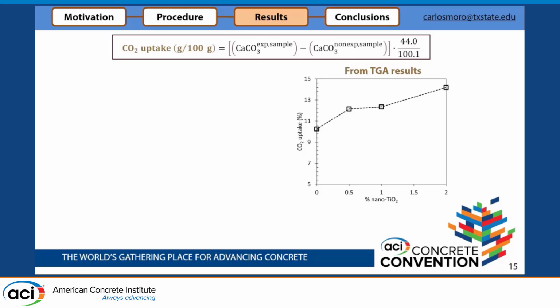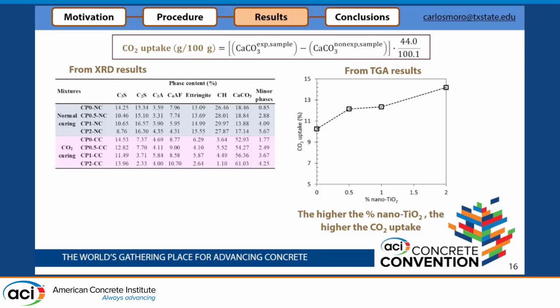These are for TGA results. Then we also did that for XRD. We did XRD analysis for all these samples from 0, 0.5%, 1%, and 2%, and we did the Rietveld quantification. That means quantitative XRD, and we quantify all the different phases that in these samples we could get the crystalline phases.